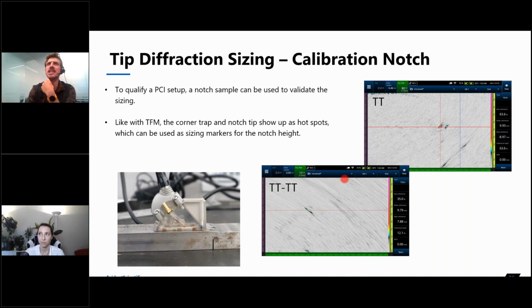So by using the TT and the TT-TT groups, we can see the tips of our notch coming off as a bright point, a hot spot, and we can basically just place our reference cursor directly on that point, and then using our readings, we know automatically what the size of our notch is, which is something you can do also with amplitude-based methods, but the actual tip diffraction is going to be much easier to see using PCI. And obviously this calibration block is a very clean sample, so there's not a whole lot of noise that can cut out or hide the tip diffractions in TFM, but when we come to a real sample, it's going to be a lot harder to see.